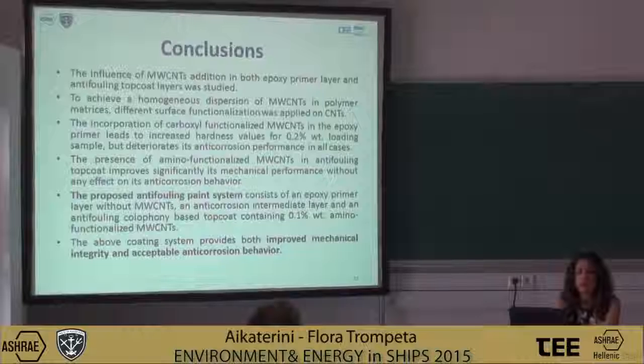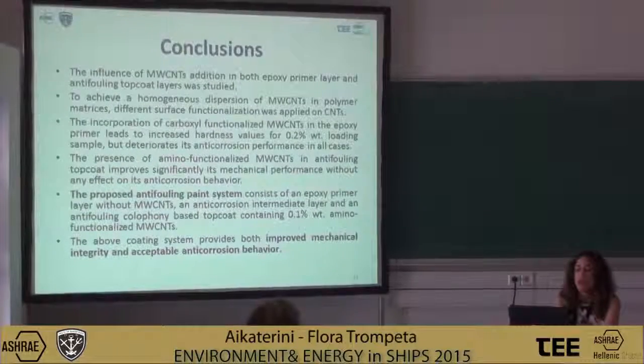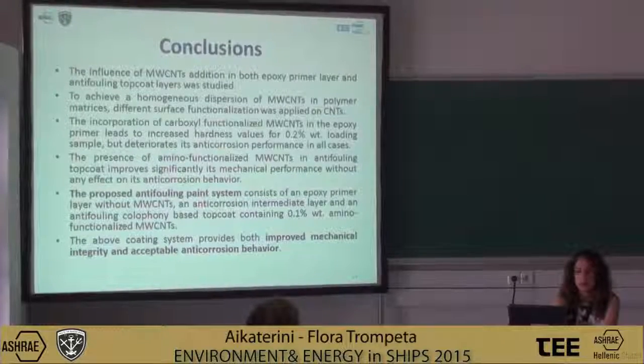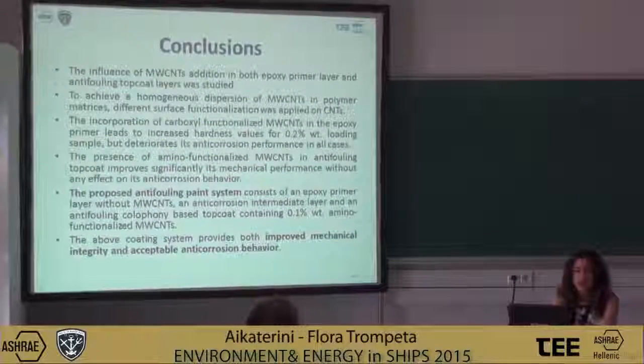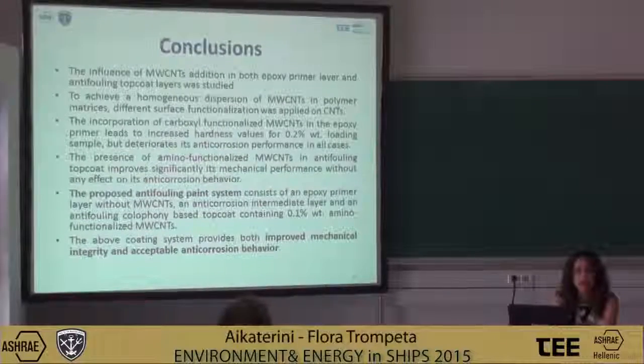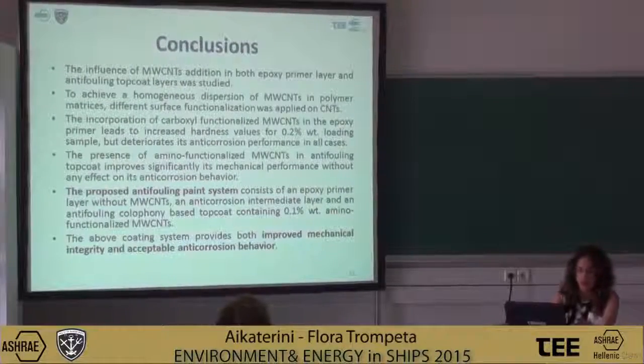Also, the presence of the amino-functionalized CNTs in the antifouling top coat improved significantly its mechanical performance without any effect on its anti-corrosion behavior. So, if we would like to conclude to a specific system, the proposed antifouling paint system can consist of an epoxy primer layer without CNTs, an anti-corrosion intermediate layer, and finally an antifouling colophony-based top coat, a CDP system as was referred to before, containing 0.1% of the amino-functionalized CNTs. So this system can provide both improved mechanical integrity and acceptable anti-corrosion behavior.